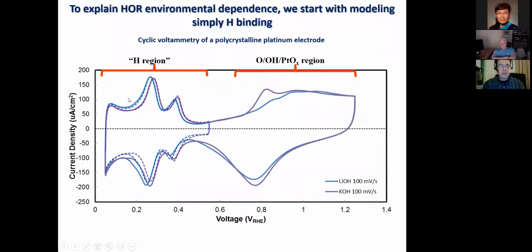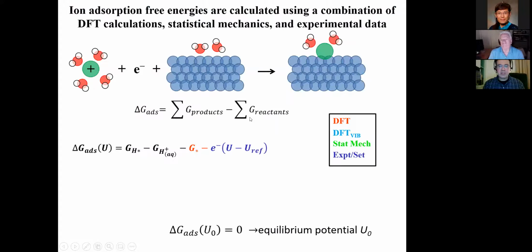And this is a textbook example. If you grab Bard and Faulkner electrochemistry, they'll explain to you exactly what this is, and they'll call this the hydrogen region, because what's going on here is hydrogen that was on the surface of the platinum when I started my experiment is coming off. It's going into solution as protons and electrons, leaving behind a bare surface. And if I ran that experiment not with polycrystalline platinum, but with a perfectly flat platinum 111 single crystal, then I would see a broad feature that's underlying this set of peaks. This sharp peak would come if I ran a platinum 110 surface. That would be the only peak in this region. And this would be the only peak if I did a platinum 100 single crystal. Essentially any other parts of polycrystalline platinum can be approximated because these are the hexagons or the triangles of platinum. These are the squares, and these are the kind of rough part. And we're not going to worry too much about this region, but this is the OH region, where it's thought that water would oxidize and eventually you form platinum oxide.